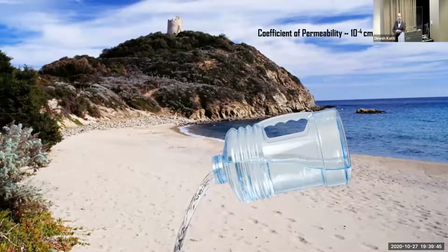And so what does that number, 10 to the power minus 4 centimeters per second, mean? Well, if you go to a beach, take water and pour it on the sand, what happens? The water simply percolates very quickly through the sand, and it disappears. Exactly the same thing happens when TCE or toluene is poured on top of the swelling clay. Basically, the swelling clays in this clay liner are ineffective in preventing these very toxic solvents from flowing through. They're great at stopping water, but they're ineffective in stopping these solvents which have very low polarity, and these solvents don't interact much with clay. So again, the question, why does this happen?